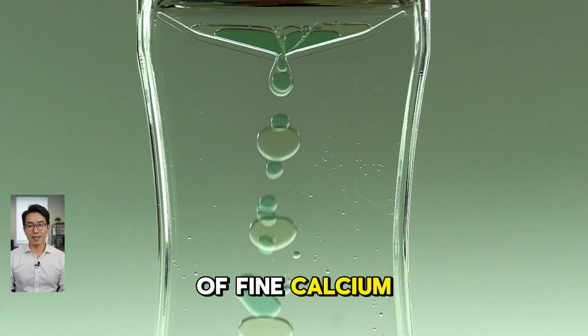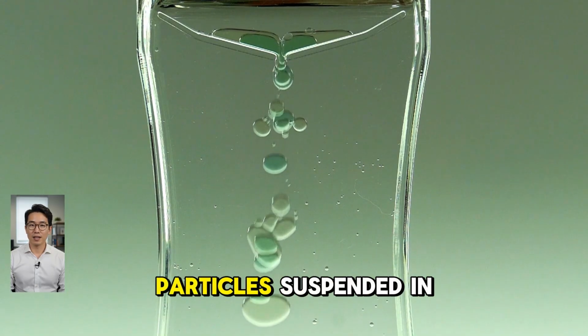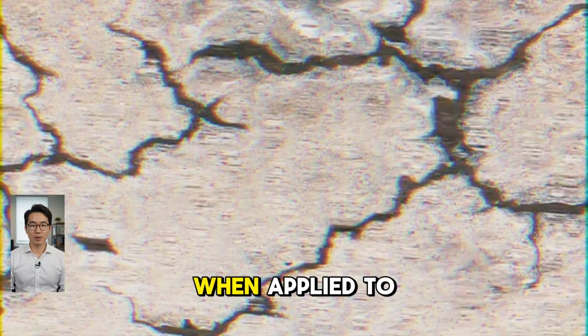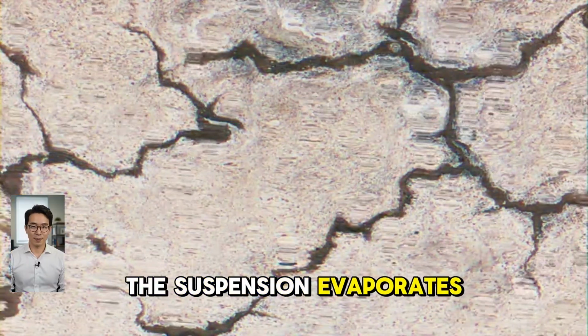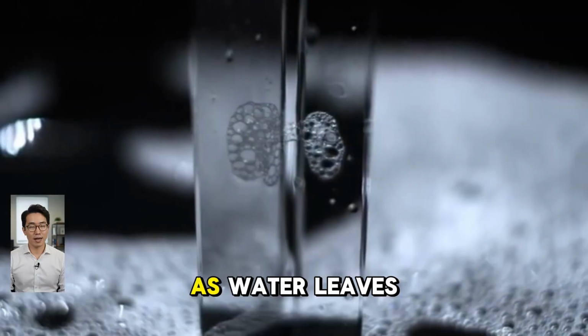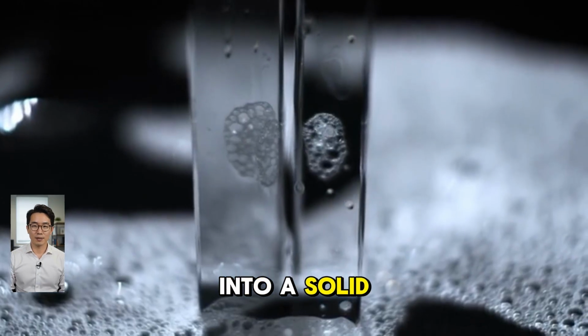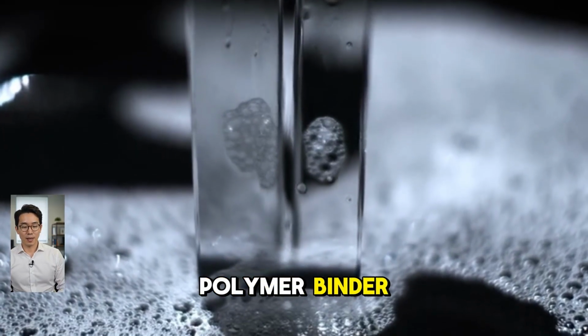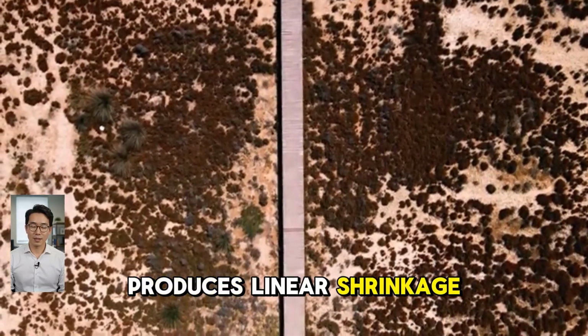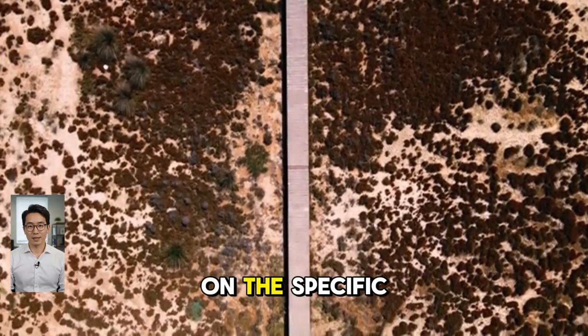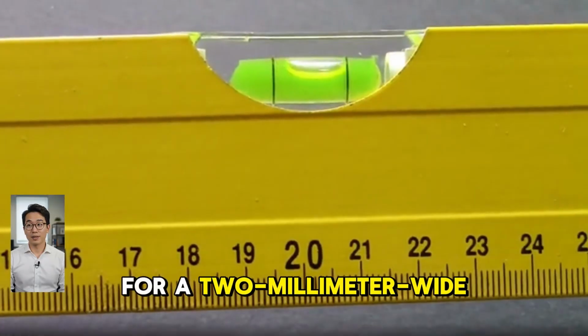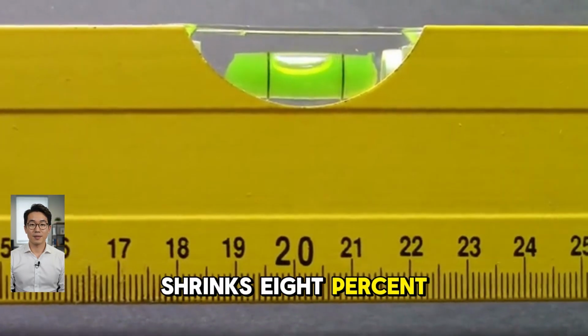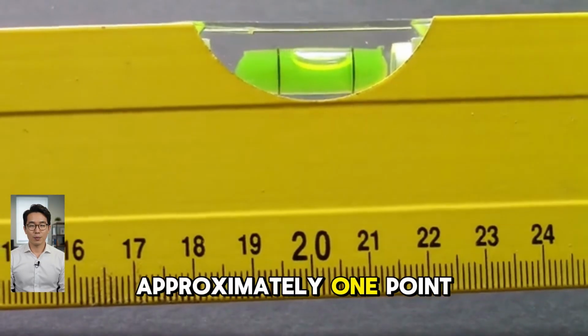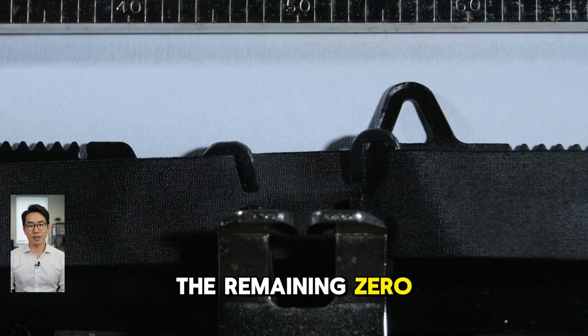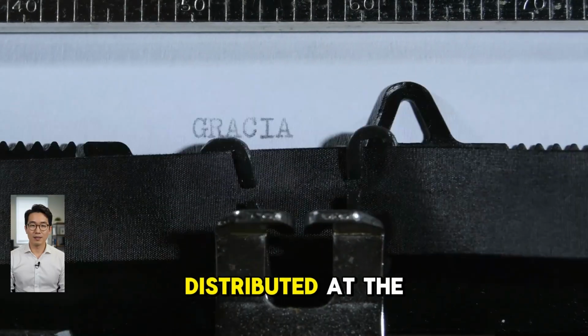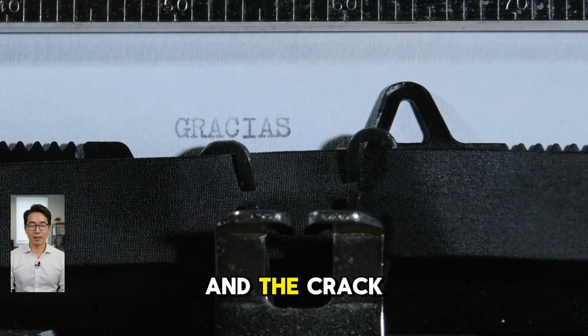They consist of fine calcium carbonate or calcium sulfate particles suspended in a water polymer matrix. When applied to a crack, the water in the suspension evaporates through the surface of the applied material. As water leaves, the particles pack together into a solid mass that is held together by the remaining polymer binder. The drying process produces linear shrinkage of 4 to 8% depending on the specific product formulation. For a 2 millimeter wide crack filled with a compound that shrinks 8%, the cured repair is approximately 1.8 millimeters wide. The remaining 0.2 millimeters of space is distributed at the bond interfaces between the repair and the crack walls.